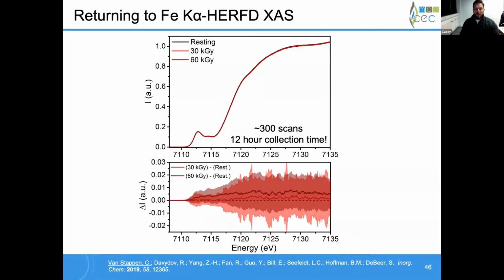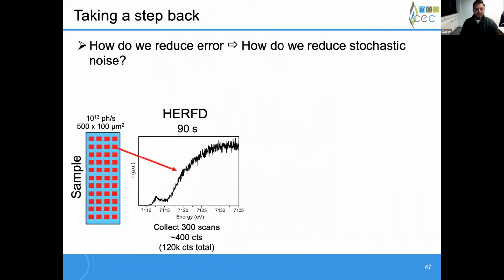And so this is one of the very few flaws I find with HERFD, is that you have relatively fast scanning times. And so intrinsically you end up at a state where you'll kind of level off in terms of how good your signal to noise ratio can get. So the question then becomes, if we want to look at the system and answer these questions using X-ray absorption spectroscopy, we need to reduce those error bars. And in that case, really what we need to do is reduce the level of stochastic noise in our experiment.